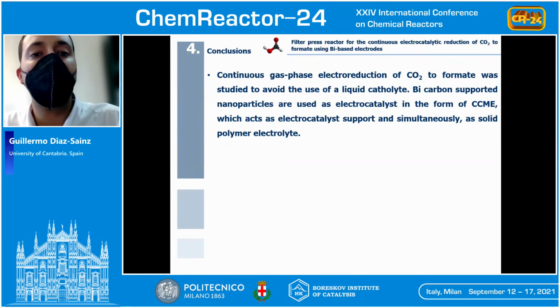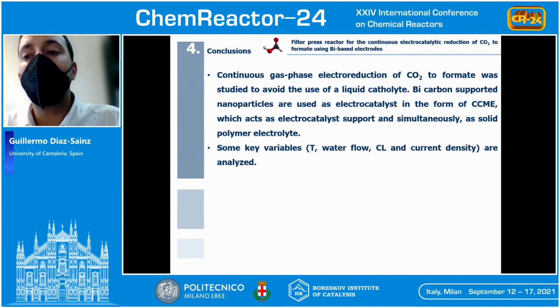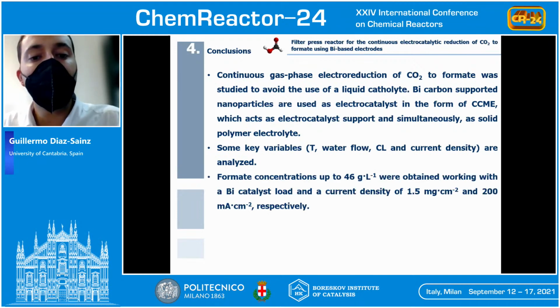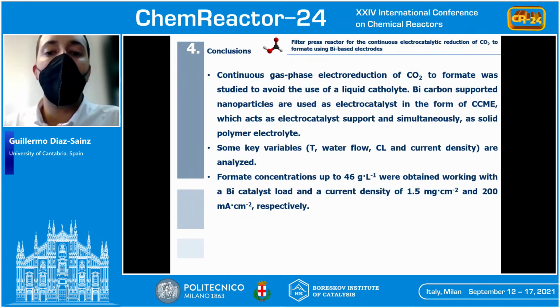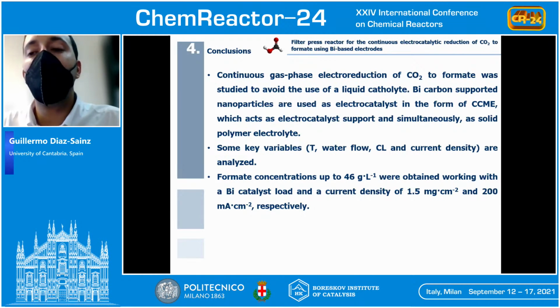In addition, bismuth carbon-supported nanoparticles are used as electrocatalysts in the form of a catalytic coated membrane electro-configuration, and some key variables are studied: the temperature, the amount of water in the humidified carbon dioxide input stream, the bismuth catalyst loading, and the current density. Formate concentrations up to 46 grams per liter were obtained, working with a bismuth catalyst loading of 1.5 milligram per square centimeter and a current density of 200 milliampere per square centimeter. But this concentration could be obtained at the expense of worsening the other figures of merit, that is the Faraday efficiency, the formate rate, and the energy consumption.